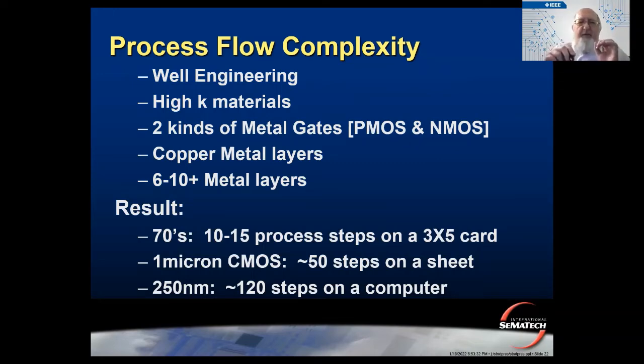The effect it has is that the process flows have been growing asymptotically. Well engineering that I showed you in the implants, high K materials, two metal gates. I haven't even talked about copper itself. And you've seen in many places, people advertising that they're doing 6 to 10 metal layers. Each of those is additional process steps that have to be carried out and built in. So what I see, and interestingly, this is over my career and probably a fair bit of yours, as it were. When I started work in the 70s, there was 10 to 15 process steps, which were on a 3x5 card, which was taped to the top of the 3 or 4 inch wafer box. And that's what you did.